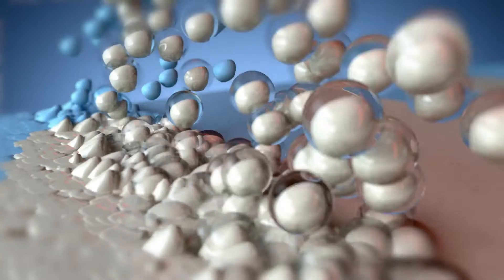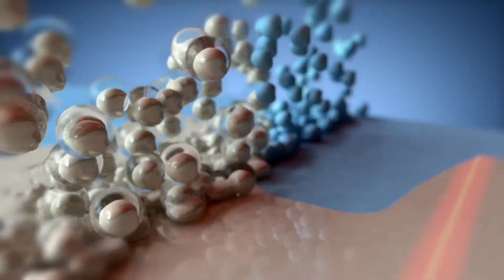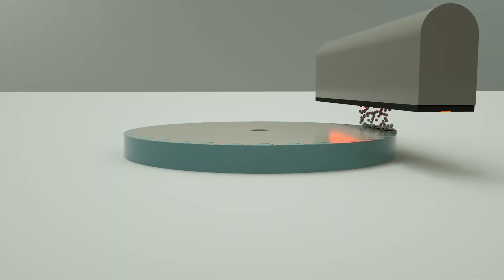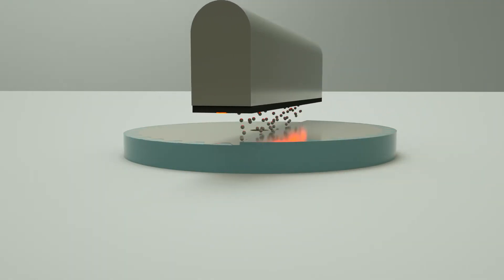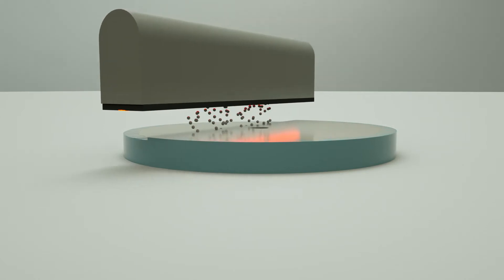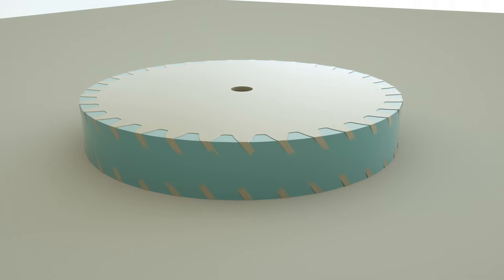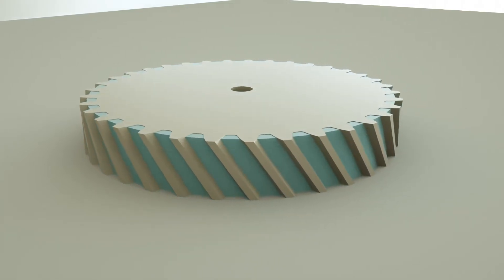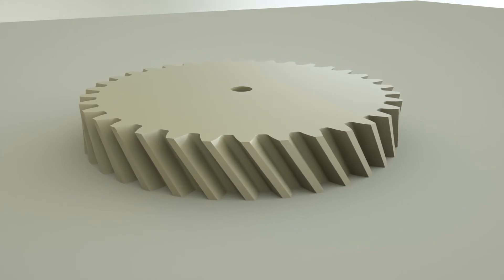Liquid droplets, containing either ceramic model or support materials, are simultaneously deposited onto the build tray in an ultra-fine layer. The ceramic part builds up as the tray descends with each pass of the inkjet printheads. After printing, the support component, made of a soluble material, is easily disintegrated, allowing for fast and clean support removal.